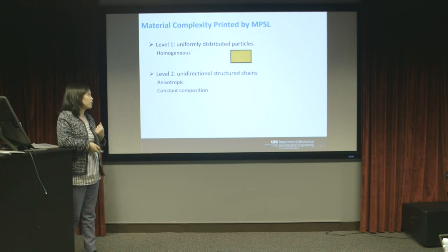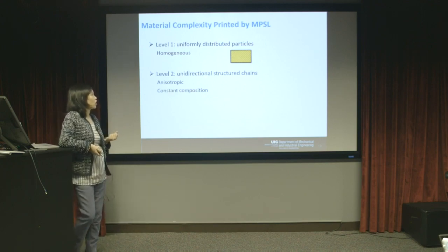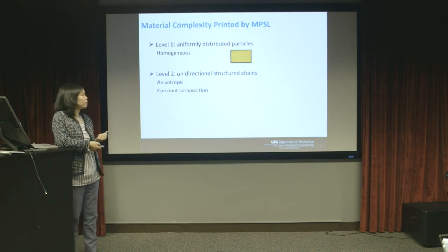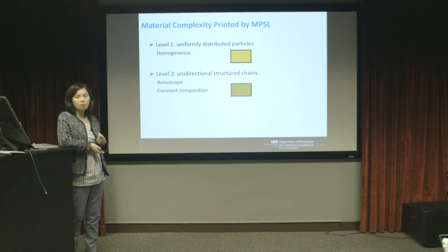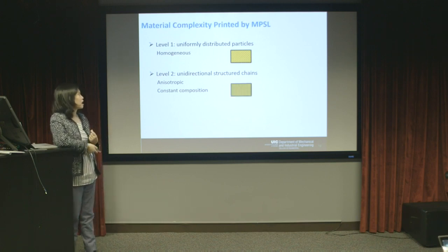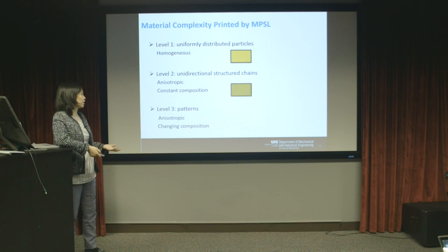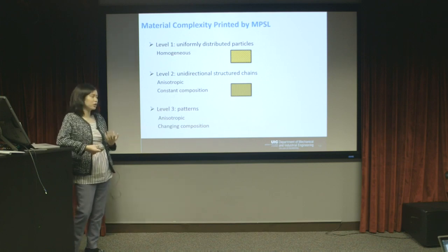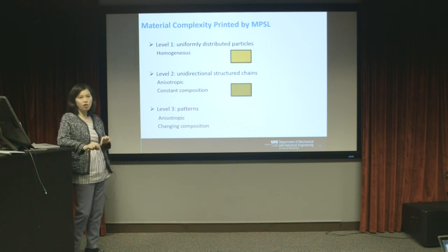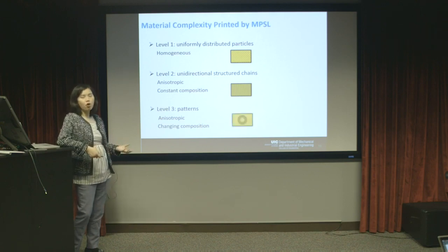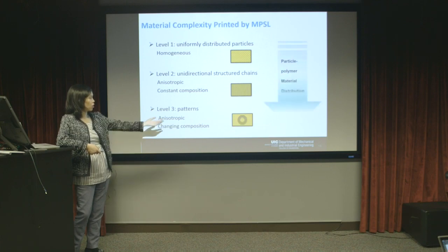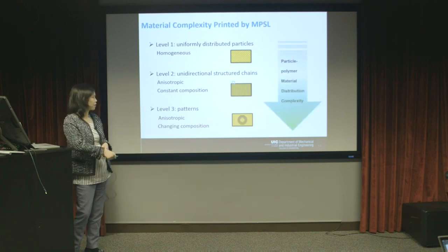But at the second level, you can achieve unidirectional structural chains. In this way, you can fabricate anisotropic composites. However, at this level, you still have constant material composition. So the third level is that we want to change and control the material composition locally, so you can fabricate something more complicated. Like what's shown here, a circle pattern in the polymer matrix.